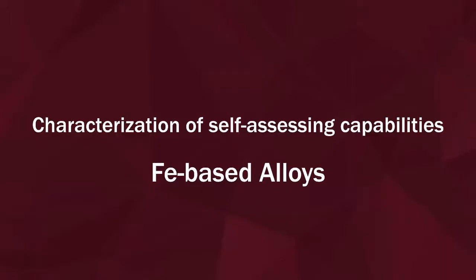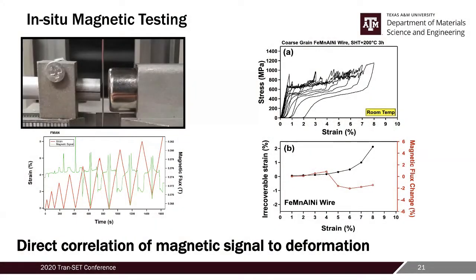Let's look at the self-sensing capabilities of iron-based SMAs. Like I said, these materials show a magnetization change during this phase transformation. So we wanted to take advantage of this property and build self-sensing sensors out of these materials. This is our setup, this is our sensor, and you place a magnet, and this is the wire that we measured. We continuously recorded the magnetic signal change during this superelastic test.